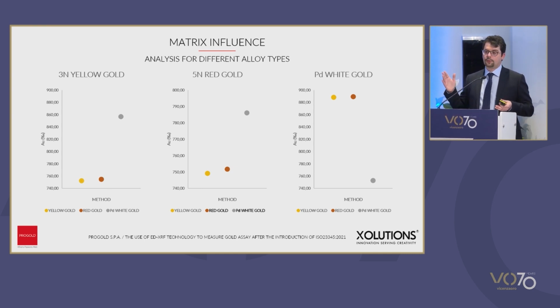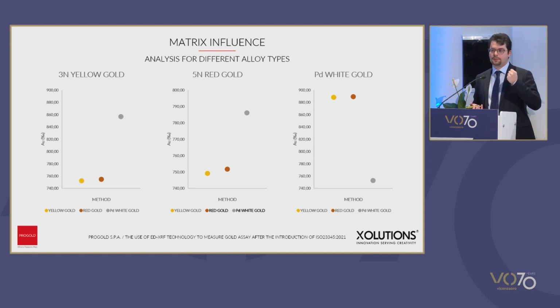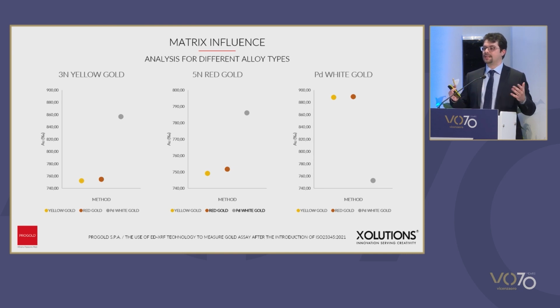And we see it here. Basically, there is a wide error if we use the white gold method with red and yellow gold alloys, and vice versa, because there is an element which is completely different, and which is palladium, which causes variations in terms of results. And there are also variations between yellow gold and red gold, which have the same composition. So basically, we shouldn't use methods for different colors, but if we concentrate on just one color, so let's take our red alloy, and instead of analyzing it with its specific method, we can use methods for other red gold alloys with a higher copper percentage.